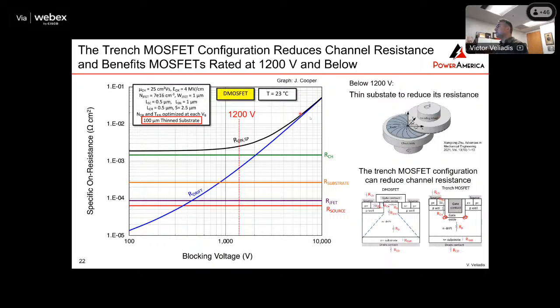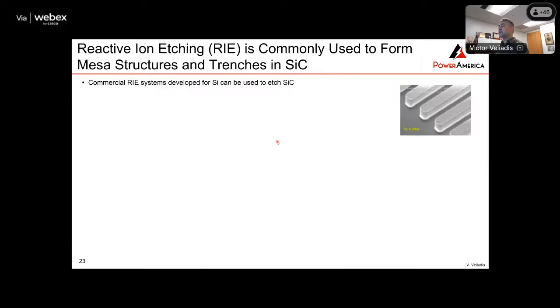And the way you thin the substrate, you put the wafer in this grinding wheel, and then you use the grinding wheel and you take the wafer from 350 microns, which is how you buy it, down to 100 microns to reduce the substrate resistance. Okay, so how do you do the etching?